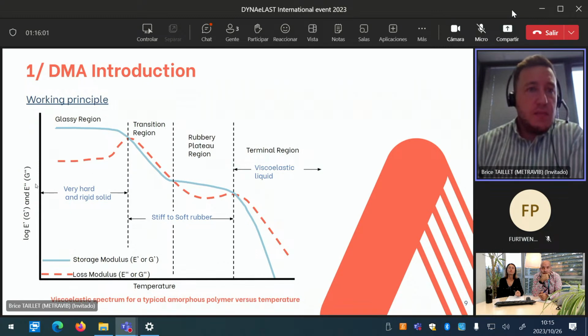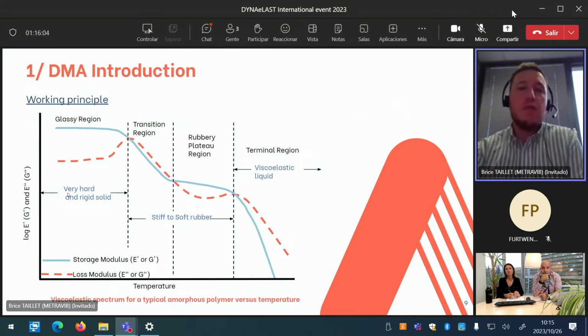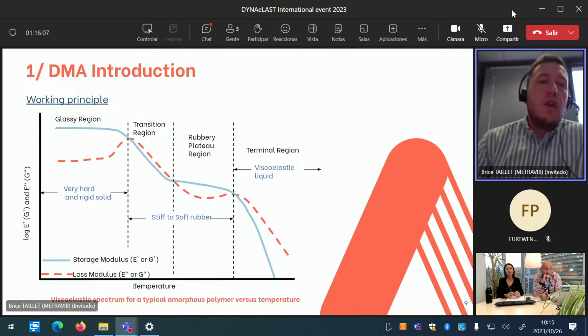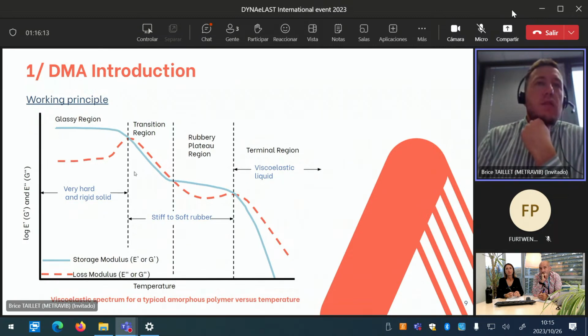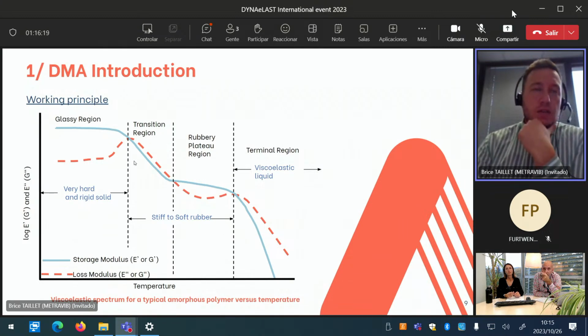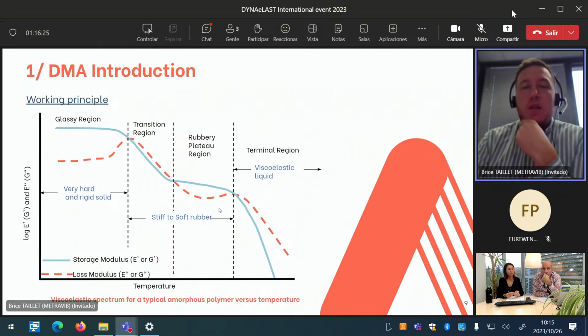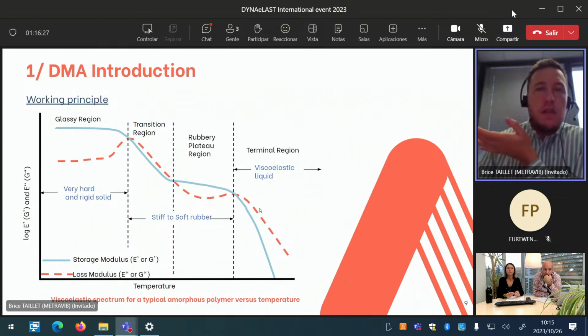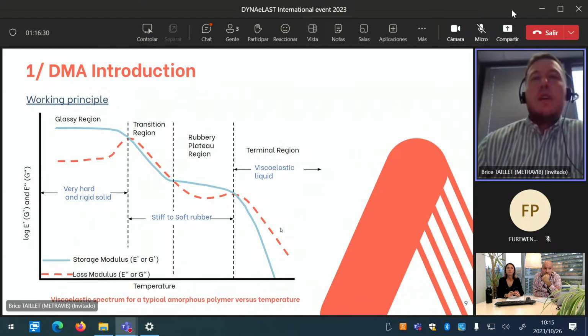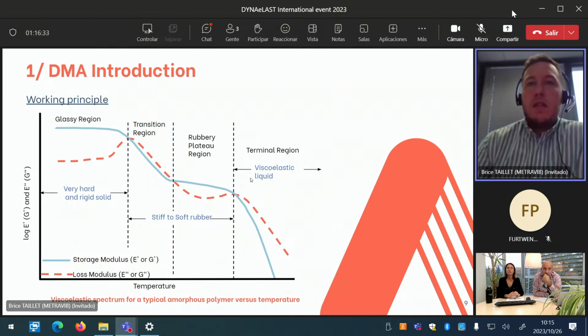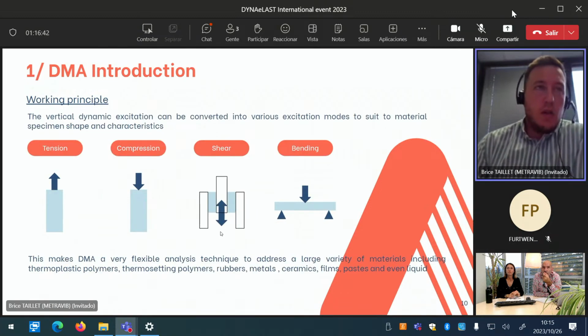This is a viscoelastic spectrum for a typical amorphous polymer as a function of temperature. And in DMA, we are able to characterize the glassy plateau, the transition region, of course, with primary transition, such as glass temperature, for instance, the rubbery plateau, and sometimes, depending on the instrument we can use, or depending on the kind of materials, we can also characterize the viscoelastic and the liquid part in the final region of this spectrum. Okay.